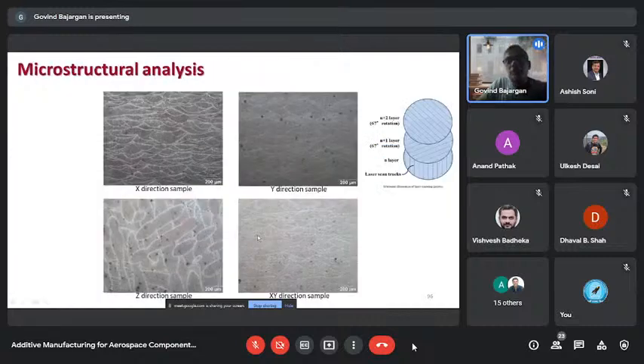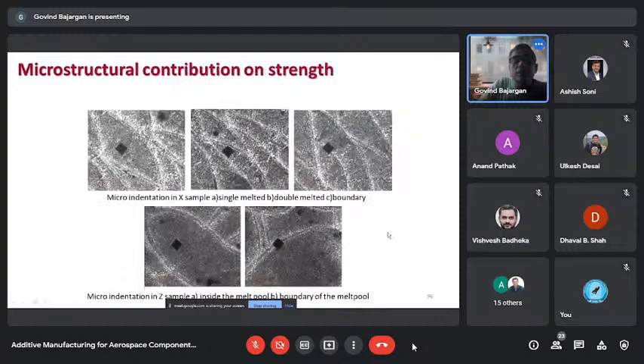This is a microstructure of one of the samples, one of the prints we have done long back. This is the aluminum. You can see the laser tracks here. This is the previous scan, and there is a 67-degree next scan. So laser tracks are very clearly visible, and there is the orientation of 67 degrees. The hardness we have checked, and we didn't find much of a thing.